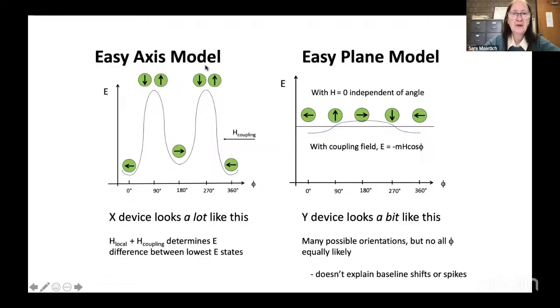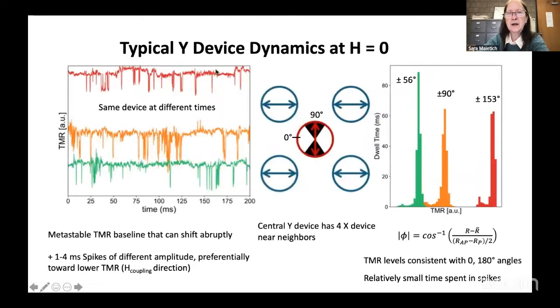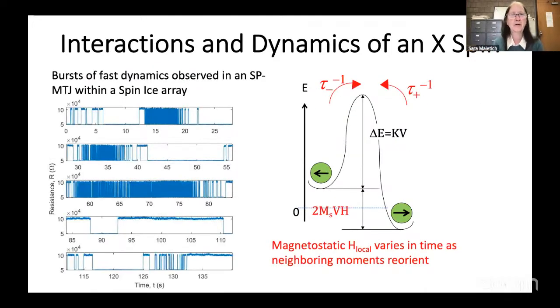Whereas these Y devices are starting in this high energy state. So they don't have the option to go down to a low energy state because of the local field. They act more like what would be called an easy plane model, where the moment can rotate at different angles within the plane, but doesn't go perpendicular to the plane. If we put in the coupling field, there's a slight preference for one or another, but it doesn't explain what we're observing experimentally, which is that we don't have a continuum, we have specific preferred levels, and it doesn't explain these spikes. So we have to go further to try to understand that.